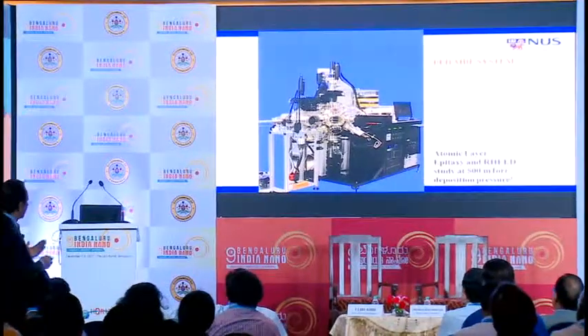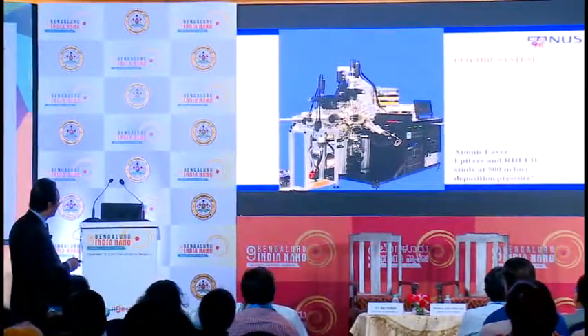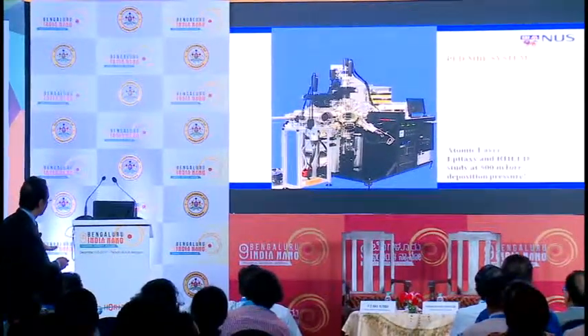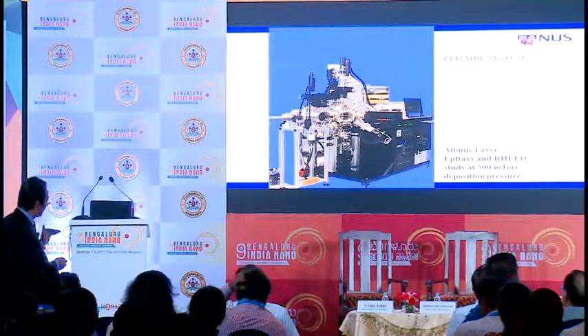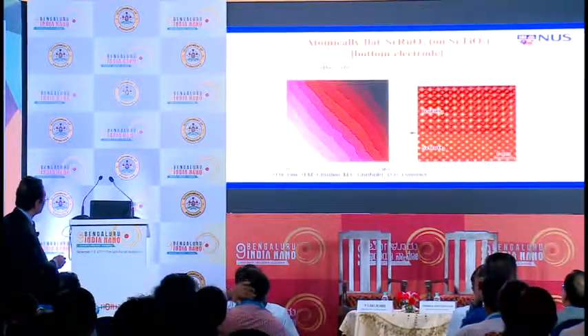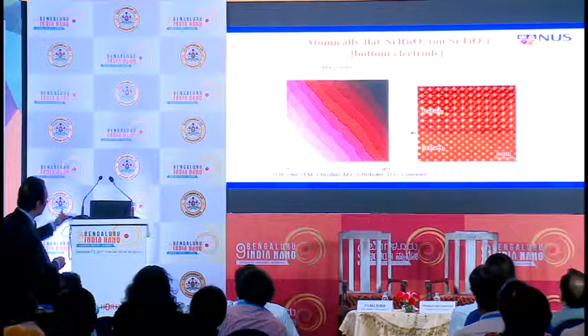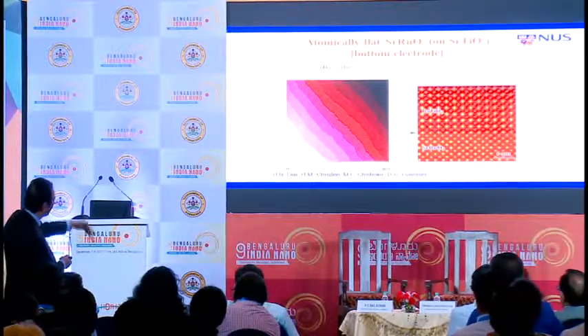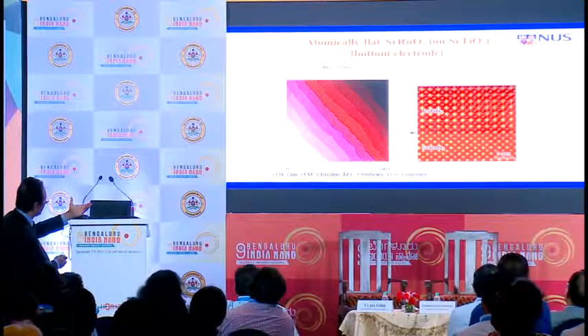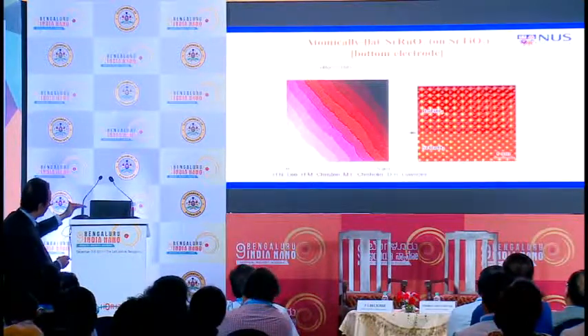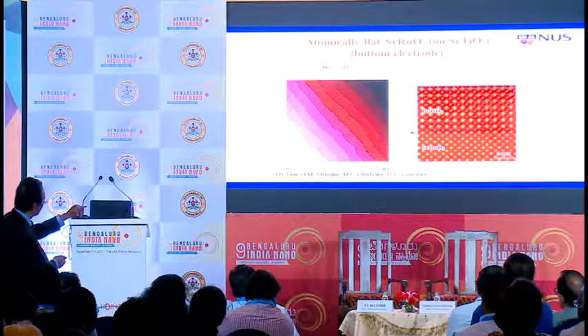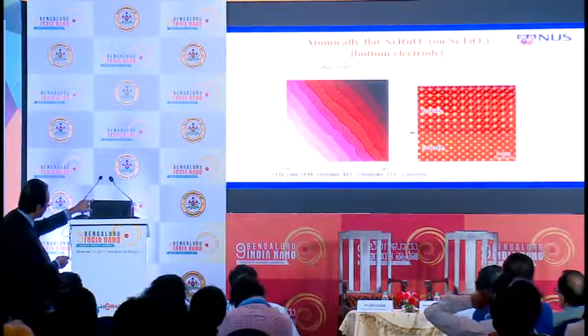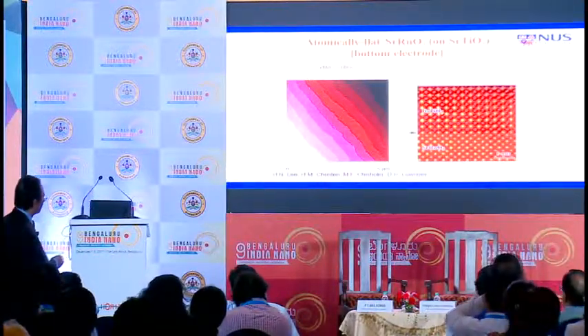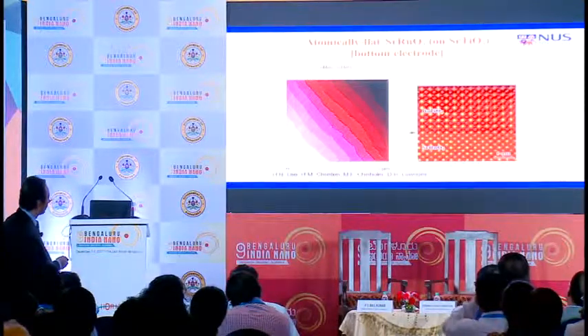Now, since this is the nano conference, I want to show you how this is related to nanotechnology, because this is a pulsed laser deposition, molecular beam epitaxial system. With this, we can actually deposit atomic layers of film. Here, for example, the PLD deposited film of barium titanate on strontium ruthenate. And this is a TEM image, and you can see these are atomically ordered images. You can see the strontium ruthenate underneath, and right at the edge where the arrow comes in is where barium titanate starts. Okay? So these are beautiful atomic crystals that we're making.